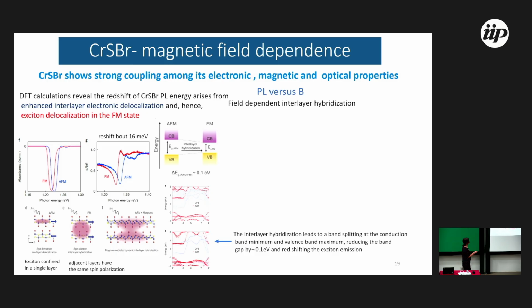Due to this interlayer hybridization, the gap for the antiferromagnetic phase and for the ferromagnetic phase are different. If the gaps are different, the exciton energy is different. So I can use the exciton, which is very easy to measure. You can use the exciton from photoluminescence to probe the phase transition.